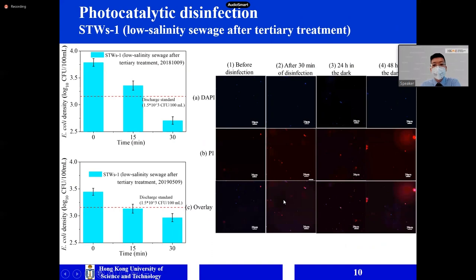Here we can see that after disinfection, the amount of red points increases, and after the settlement of the sample in the dark for 24 hours and 48 hours, there is no rebound of the blue points, and the concentration and density of the red points are stable. This indicates that during this photocatalytic disinfection process, the cell wall and the cell structure of the bacteria were damaged, and this damage is not reversible.